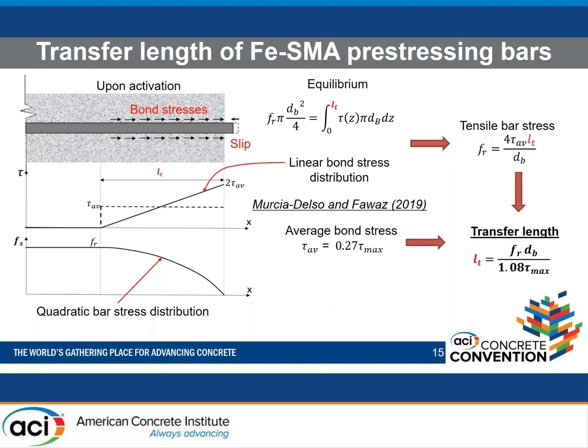So now, after understanding the bond behavior of SMA bars and the influence of activation temperature, we need to get an idea about the transfer lengths, because this will be a requirement when we are implementing those bars in practice. In order to do that, I need to do just a quick review of the equilibrium here, that we have the mechanism of these bars. So first of all, when we activate those bars, a slip will be induced, and of course this slip will be resisted by bond stresses coming from the interface between the bar and the concrete, and these will be required in order to develop the pre-stressing stress that we are assuming that the bar will achieve in order to use it for pre-stressing applications.